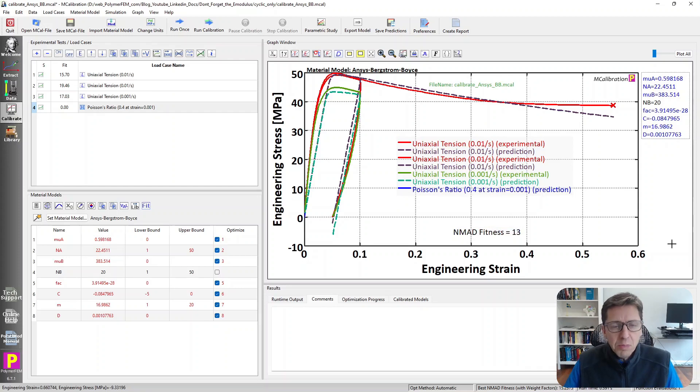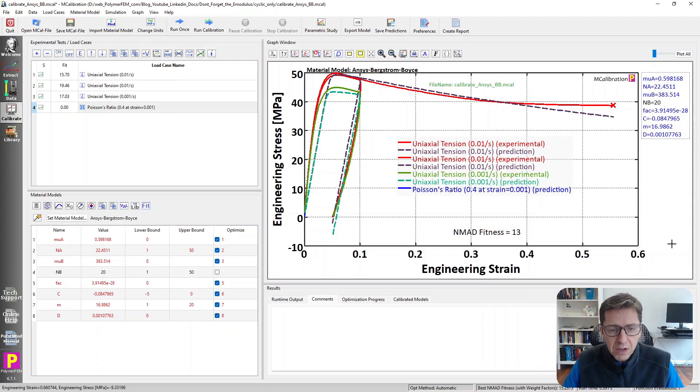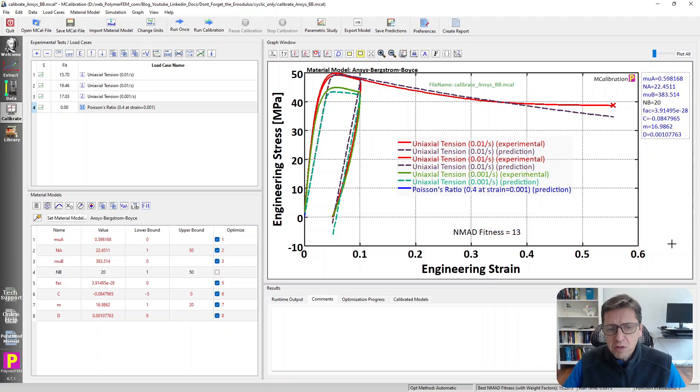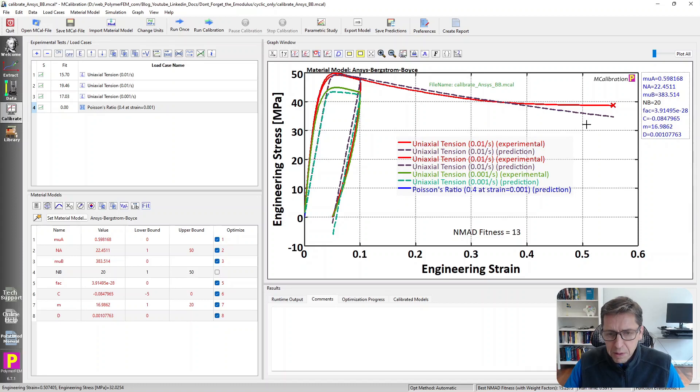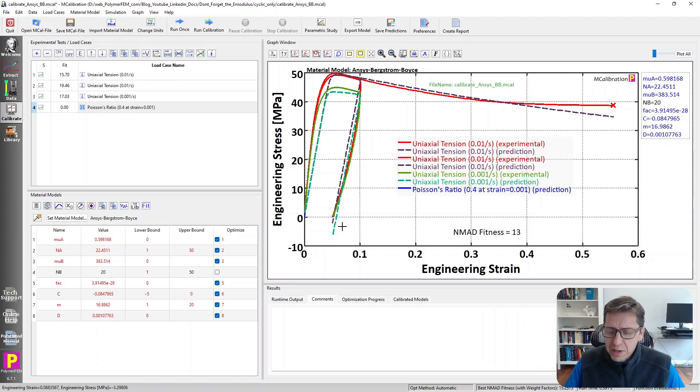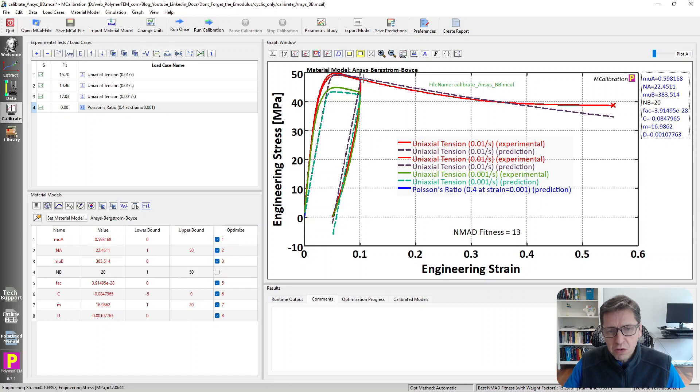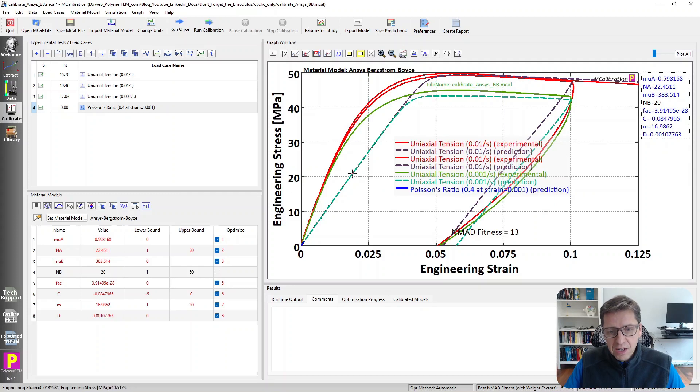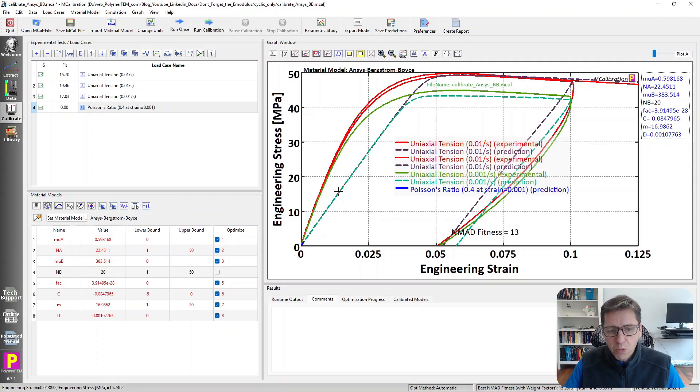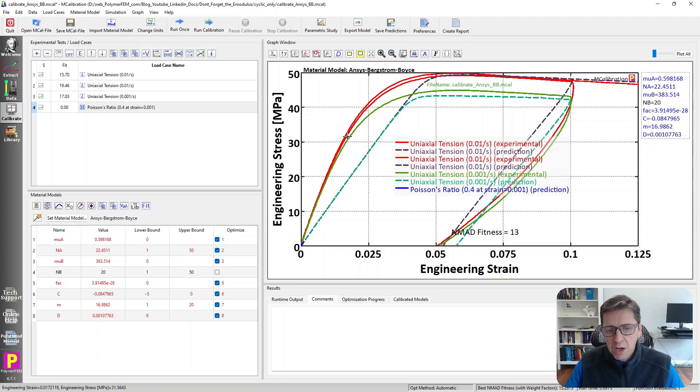So what is the problem? What did we do wrong here? Clearly, the problem, as you think about it, is that this model matches the data overall pretty well. Well, about 13% error, but it doesn't predict the initial Young's modulus very well. So if I zoom in here, I'm dragging a little rectangle, we'll see that, look at the predictions here in dashed lines. They're way below. It's a factor about 2 compared to what it should be.